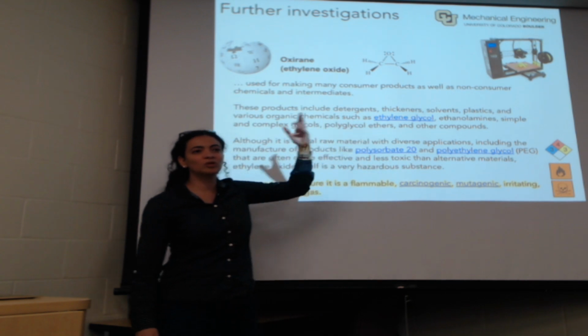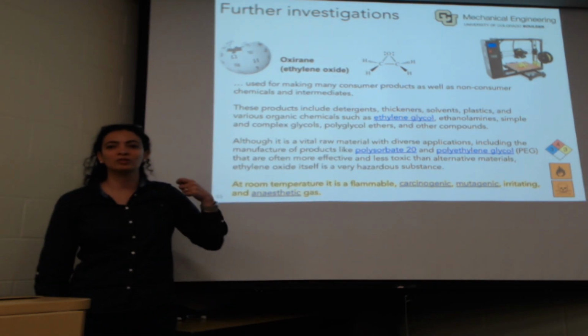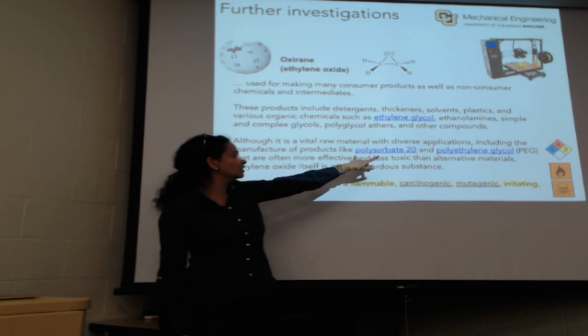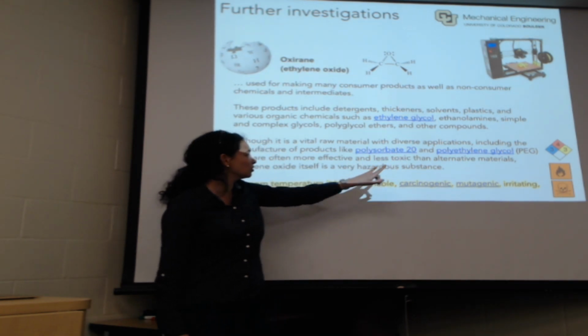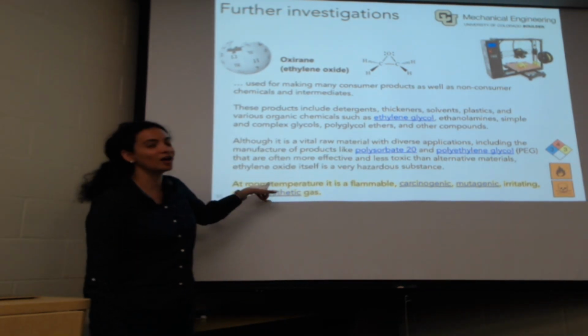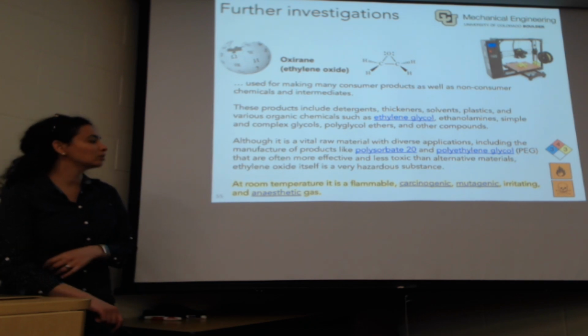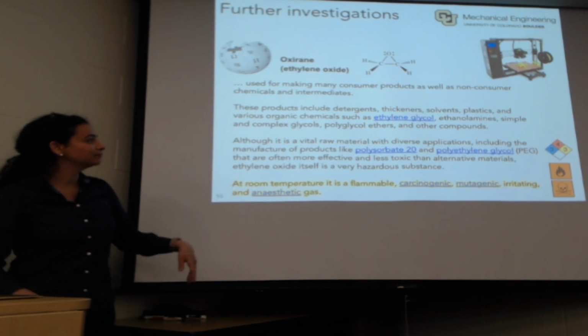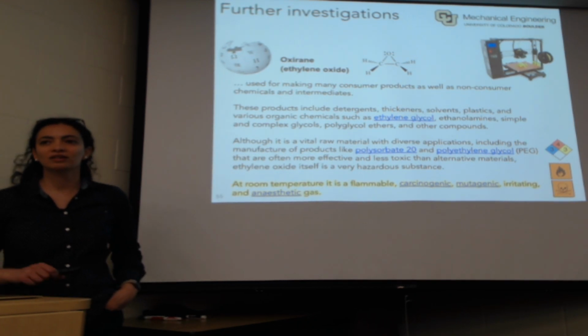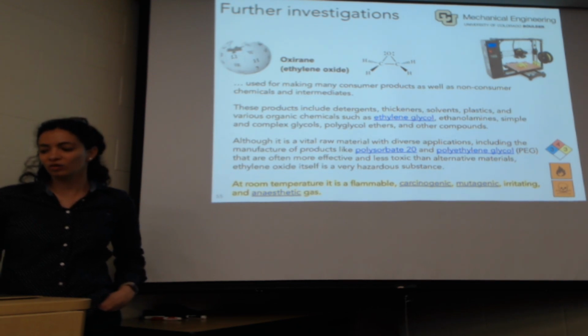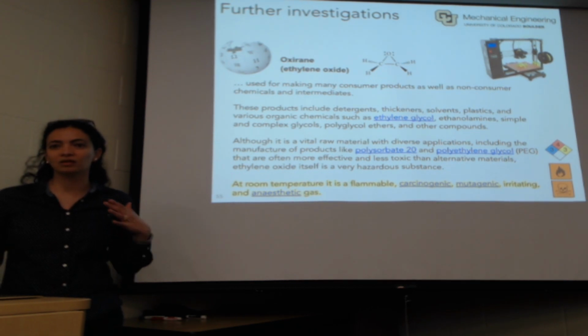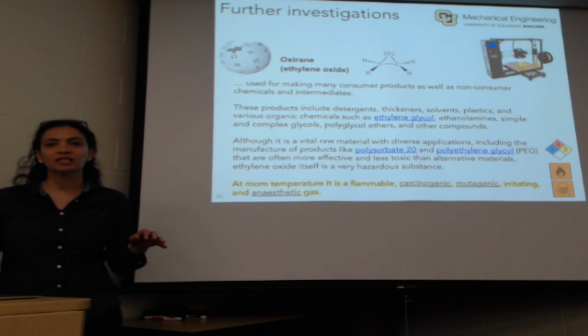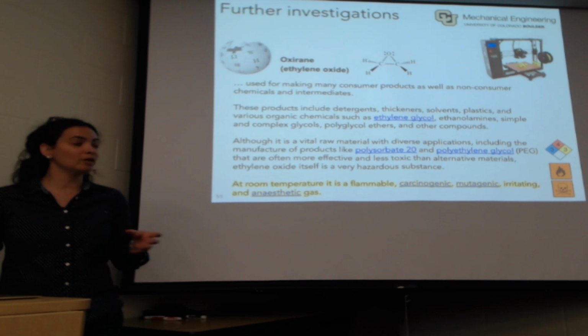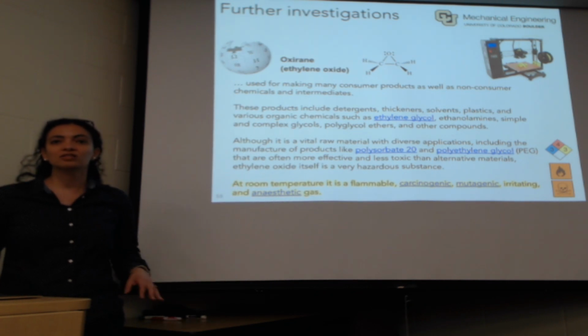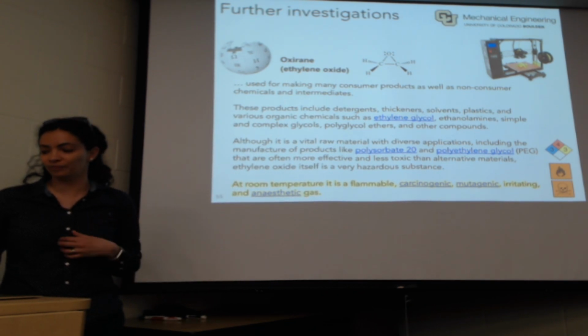But then once you put them in the filament and you run it through a 3D printer, it's possible that these are breaking back into oxirane, the precursor molecule, and emitting it, which I find rather interesting. So even though my research mostly focuses on particles, we are also looking into the gas phase for the volatile organic compounds, because they're also very important, as you can see from here. They're also very important for human health.